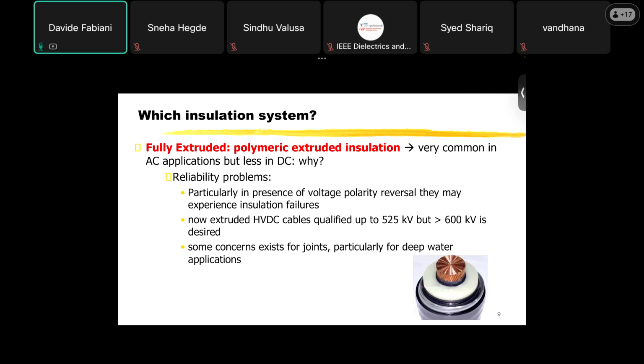In particular, these problems came when we had voltage polarity reversal. And this can occur under HVDC if you want to reverse the power. Sometimes you have polarity reversal, and this can create insulation failures. But nowadays we have extruded polymeric HVDC cables that are qualified up to 525 kilovolt. So we have developed electrical insulation that is reliable also at high voltages.